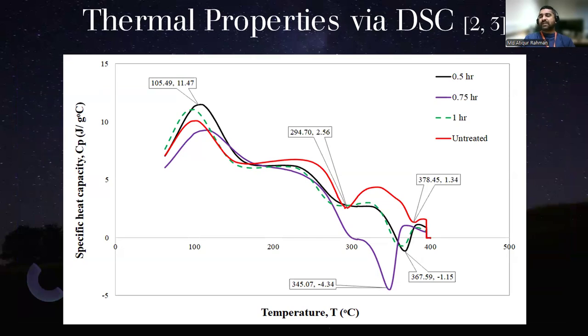We carried out the specific heat capacity figuring out process using the DSC. So over here it is pretty much similar to the TGA. The untreated fiber is marked with the red color. The first peak is, again, the representation of the moisture presence, and of course the heat capacity would be higher over there. You can see that, because of the presence of the hemicellulose hydroxyl bond. The second peak for the untreated is the representation of the hemicellulose, and the third one is the cellulose. We know the lignin is a leftover, so lignin doesn't have those types of distinct peak. However, when you did the treatment, there is no hemicellulose peak present here. So within these 3 tests, we confirmed that the hemicellulose has been taken out, if not all, at least a greater portion during this process.